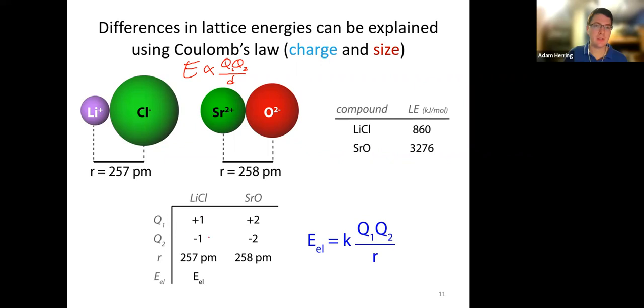When we look at the charge of the species, lithium and chlorine have a charge of +1 and -1 respectively. Strontium has a +2 charge, and oxygen has a -2 charge. Therefore, the numerator in this equation for strontium oxide is 4 times the value of that for lithium chloride. This prediction holds out really well, and we see that the actual lattice energy is pretty close to 4 times the value for strontium oxide versus lithium chloride. So our first way to predict and compare lattice energies for relatively similar sized ionic compounds is by looking at the charge of those species.